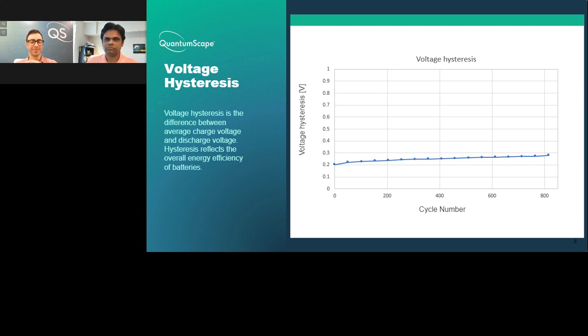On the last chart, what we were showing is the average discharge voltage during the course of a discharge per cycle. And you can do the same for the charge voltage. If you average the charge voltage throughout every cycle, you would get an average charge voltage. And the voltage hysteresis is just the difference between the average charge voltage and the average discharge voltage. Now, why is this important?